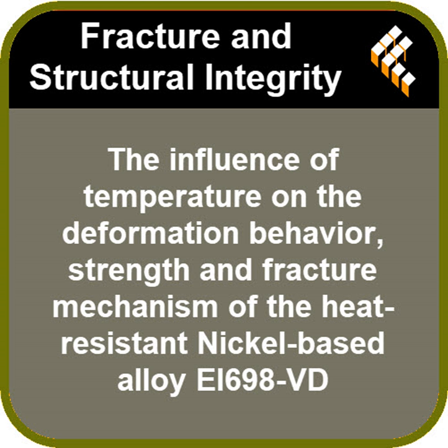Exactly. But the really interesting part isn't just the break itself. It's what happens during the stretching, between about 400 and 700 degrees. You're talking about the Portevin-Le Chatelier effect. The PLC effect, yeah. You can see it on the charts as serrated flow. It stops being a smooth curve and starts looking like a saw blade. It's all jagged.